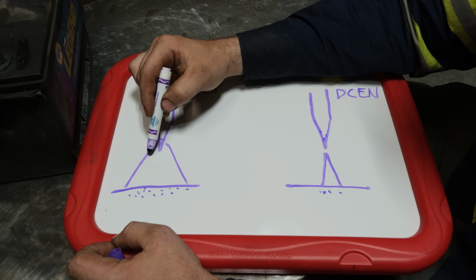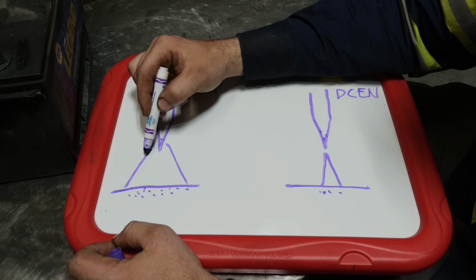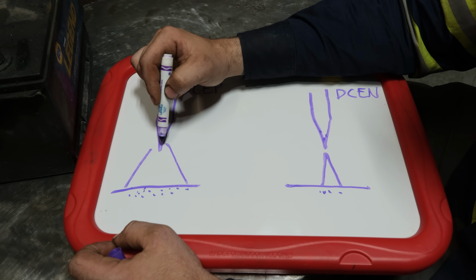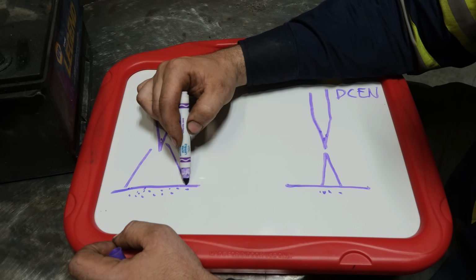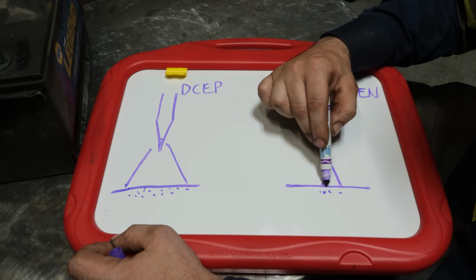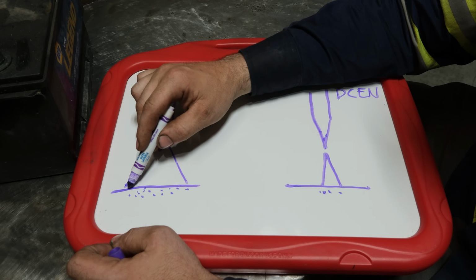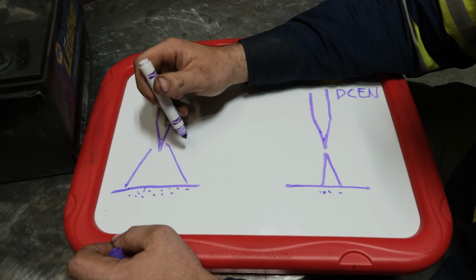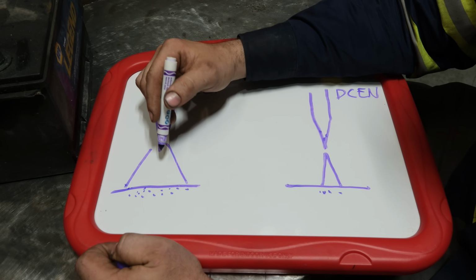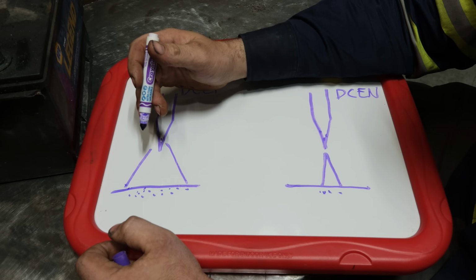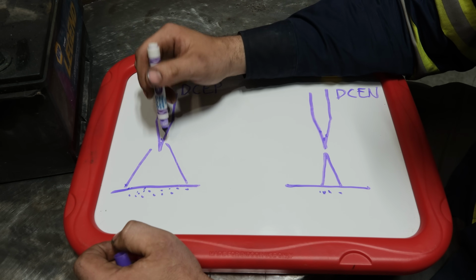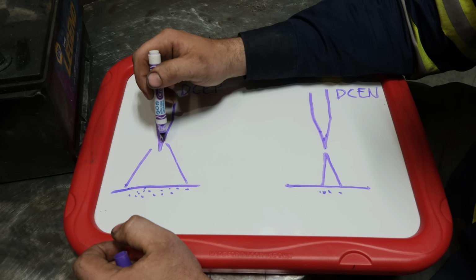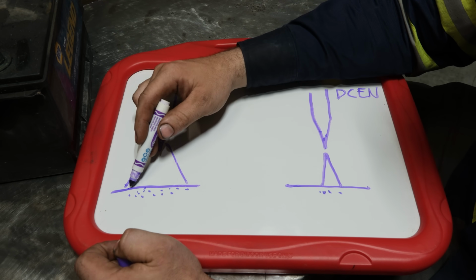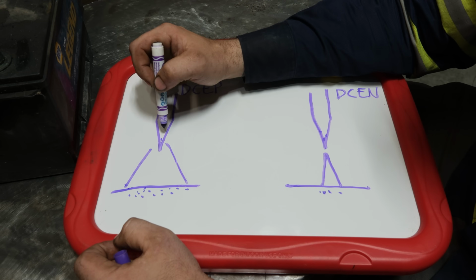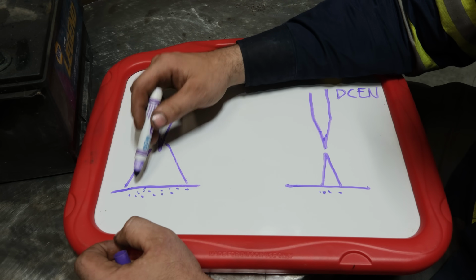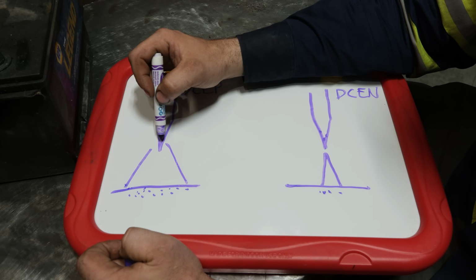Now, the downside to that is your arc cone is significantly wider. If you're trying to melt this much metal versus this much metal, it takes a lot more amperage to melt this, and your weld bead is going to be wider. That is why on AC welding, which is a mixture of both electrode negative and positive, like with aluminum with TIG, you have a very wide bead. That is simply because you're running electrode positive.